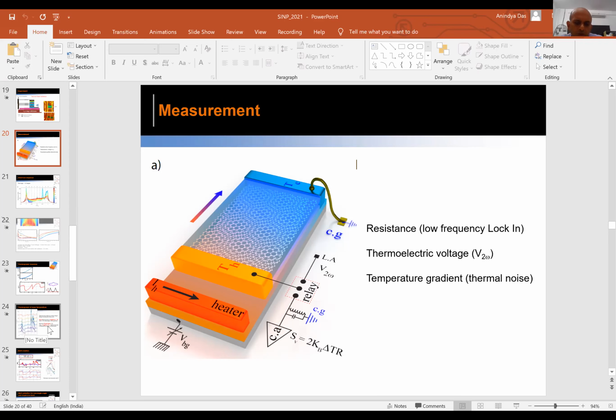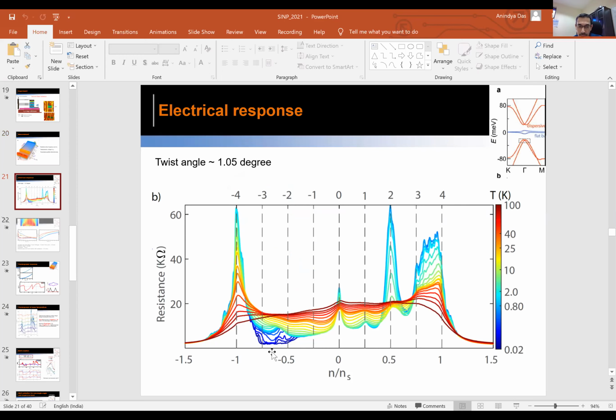And last question: is this contact resistance playing any role in your measurement? Do you face any problem? Yeah, very good question. So I'll tell you first what is the estimation of contact resistance. From this resistance data, this is a two-probe measurement. You can see when the system becomes superconducting, the lowest resistance is 1.8 kilo. The channel is superconducting, so whatever resistance remains is because of contact resistance. This flat part of the resistance gives me an estimation: the contact resistance of my device is around 1.8 kilo, roughly 2 kilo, which means the left contact has 1 kilo and the right contact has 1 kilo.